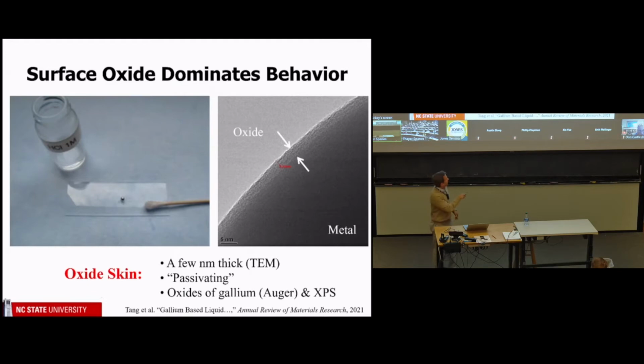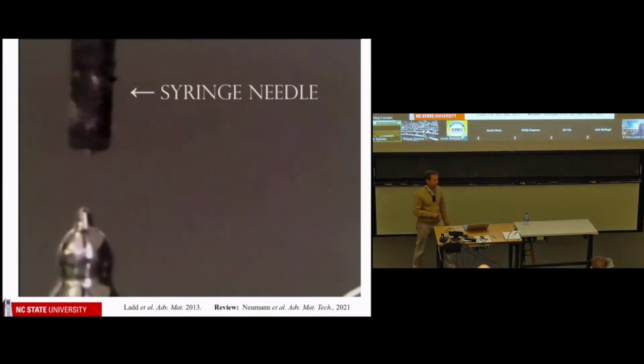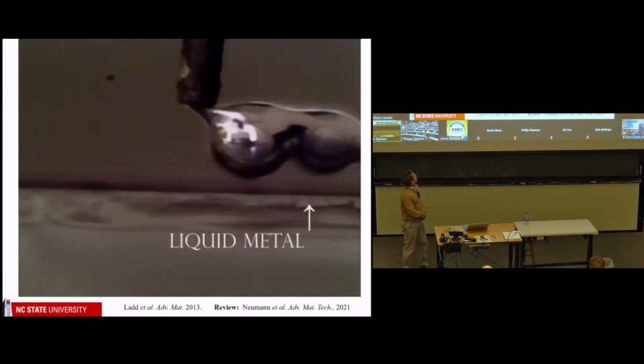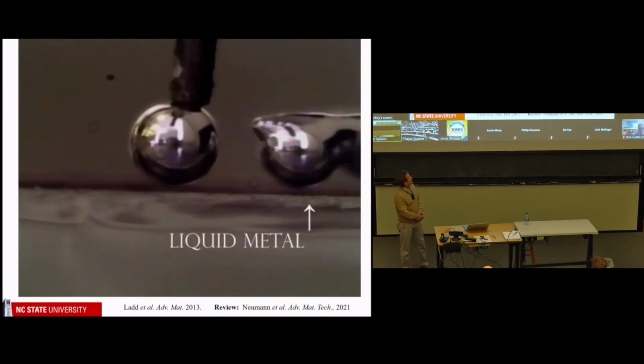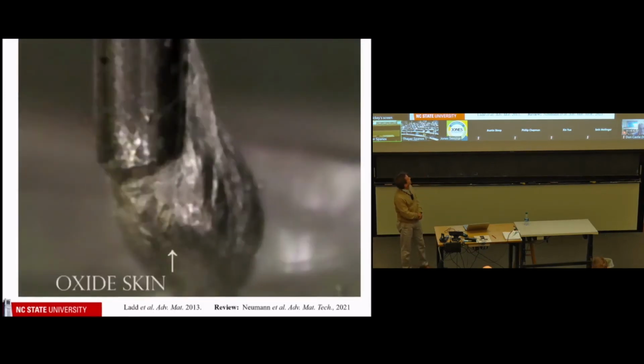Now, you might remember we added indium to the metal to depress its melting point, but that oxide is gallium oxide. It's the most energetically favorable, and it forms very, very quickly. So you might be thinking, why is this crazy guy making a big deal about an oxide layer? Well, usually, if you want a metal, you want a metal. You don't want an oxide on the surface. Well, what this does is it allows us to shape the metal, sort of like the Terminator, in ways that would simply not be possible using other low viscosity liquids.